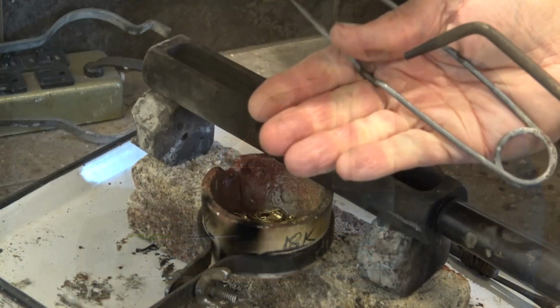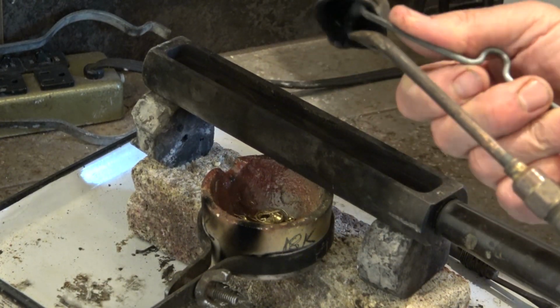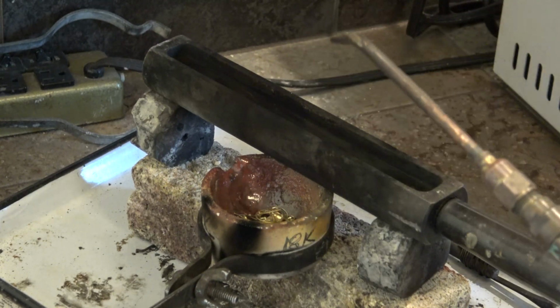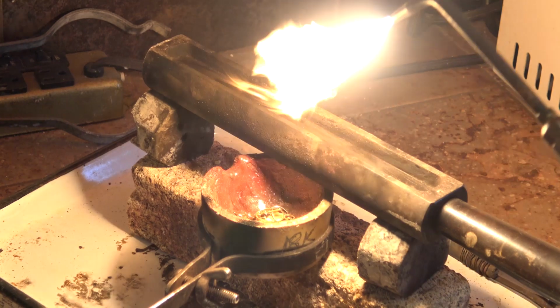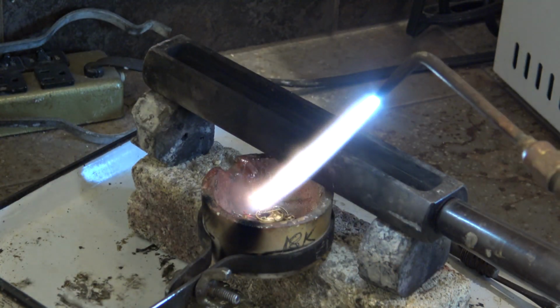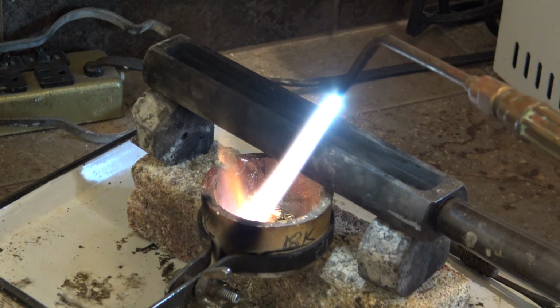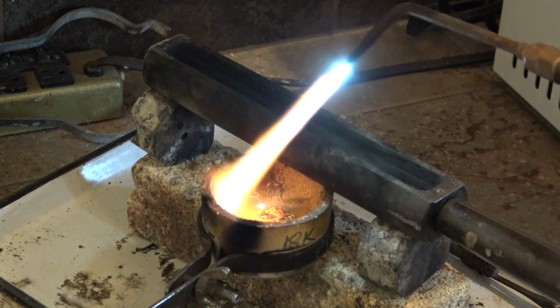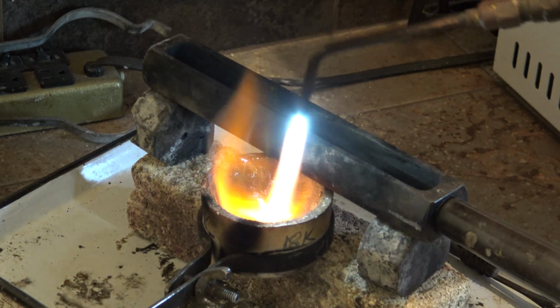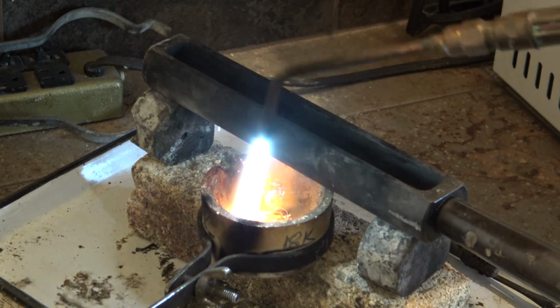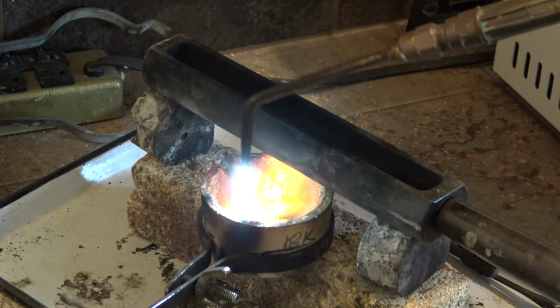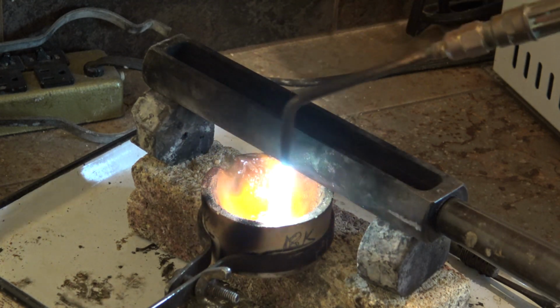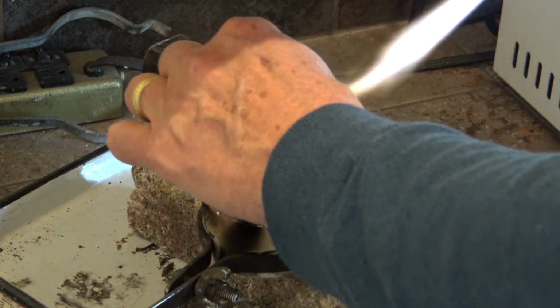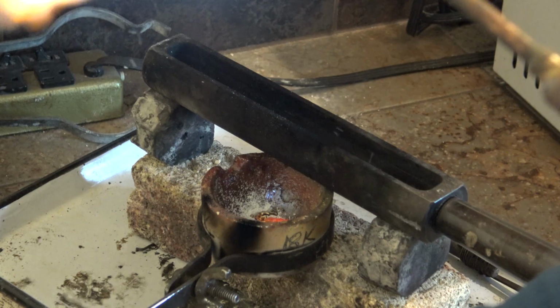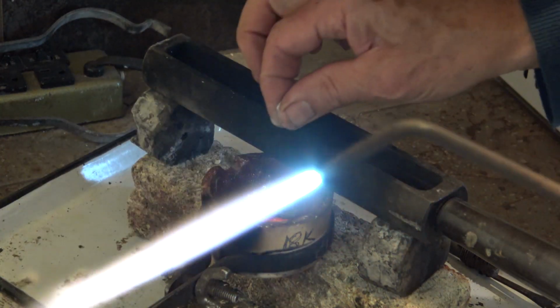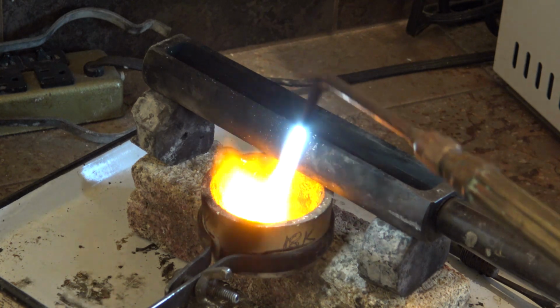Okay, so my favorite torch is an acetylene oxygen torch. I like it because it has a softer flame, it uses a little bit less oxygen than propane does, and provides more of a reducing flame for the melting of gold. Here I'm starting to melt scrap, and my flame is pretty hot. I've got a long flame. You can't really see it in the video, but it's about a 2-inch long inner blue flame just beyond the point of turning yellow. So if you added a little more acetylene or took a little oxygen off, the flame tip would turn yellow. That's the perfect flame for melting.